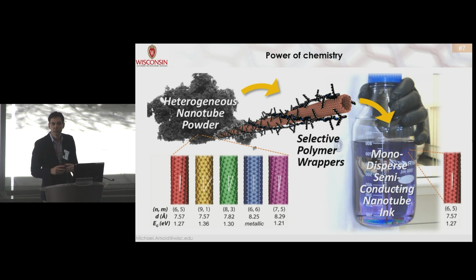Now the field has become much more savvy in terms of use of chemistry. We could take this heterogeneous powder and use surfactants and polymer wrappers that can wrap around the tubes helically, like shown here. And that wrapping could be highly selective. We could grab onto just semiconducting tubes, not the metallic ones. And we could even grab onto particular diameter ranges of nanotubes that have particular band gaps, all the way down to nearly a single structure of nanotube. So that beaker on the right is a beaker of the 6,5 carbon nanotube. It's 7.57 angstroms in diameter, with a band gap around 1.27 electron volts. And we extracted that purple color, that 6,5 nanotube, from that black powder.